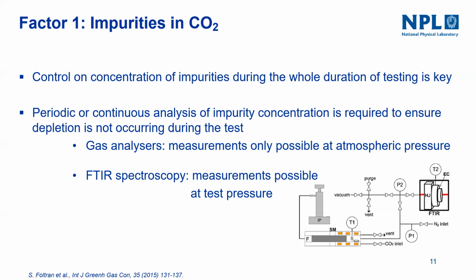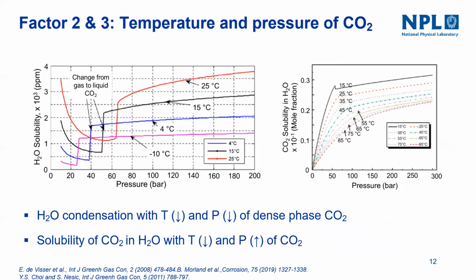Here you can see the change in water solubility in the CO2 with variation in the pressure. From gas CO2 going into the liquid phase, the solubility of CO2 varies. So if you have to measure the concentration of impurities, it is significantly different. So there could be an issue with errors coming up in the analysis.